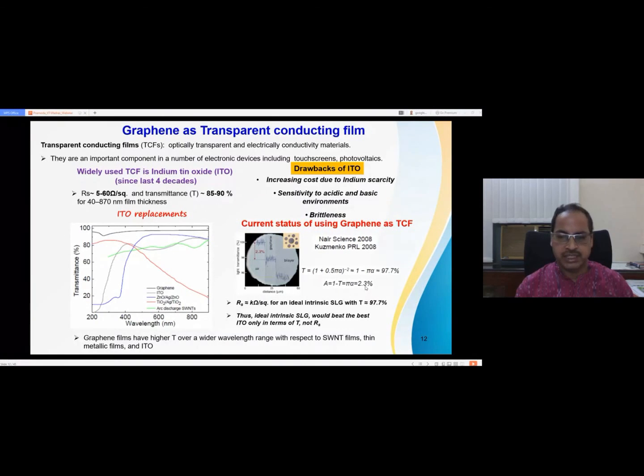Absorption is only 2.3%. So graphene film can beat ITO in terms of transmittance, but the value of the sheet resistance for single layer graphene is typically a few hundred ohm to 1 kilo ohm. Why do you call it sheet resistance? Generally, when you talk about the electrical property of a bulk material, we talk about the resistivity. But here there is no thickness, okay, because there is no Z. So we talk about the sheet resistance per square. Either you can take it per mm square or centimeter square. So the typical value is from 100 ohm to kilo ohm per square.